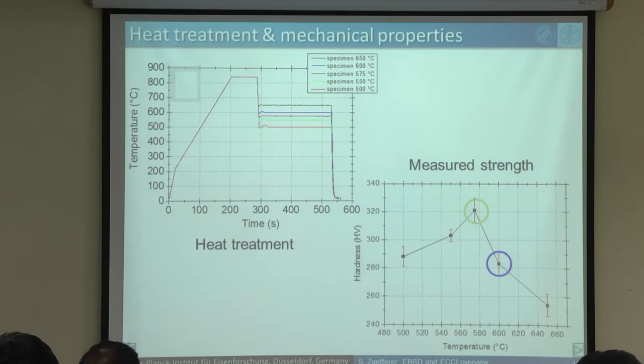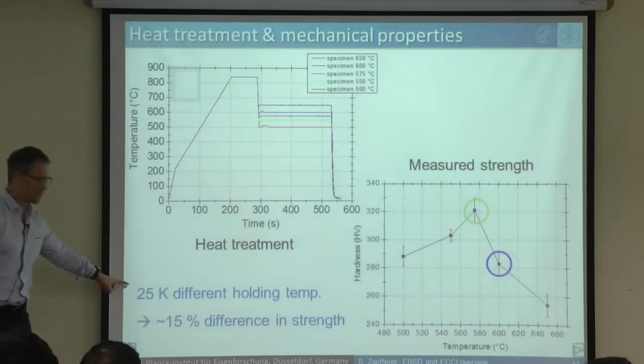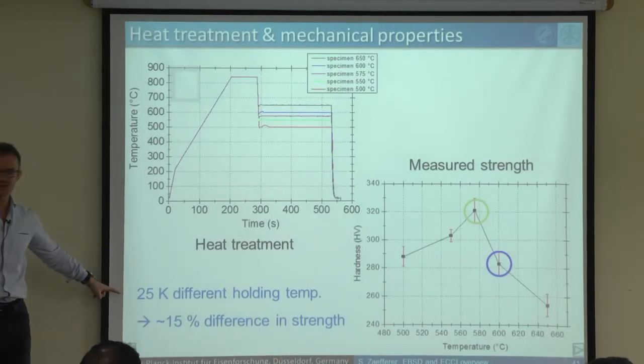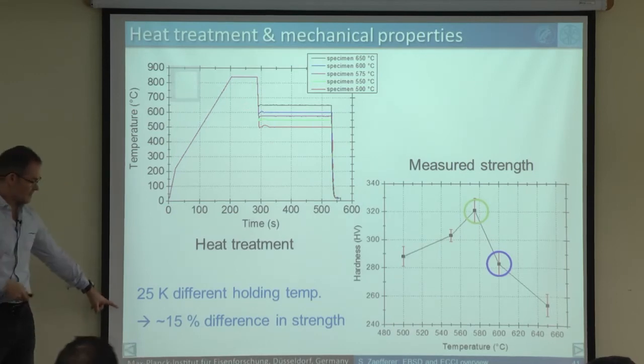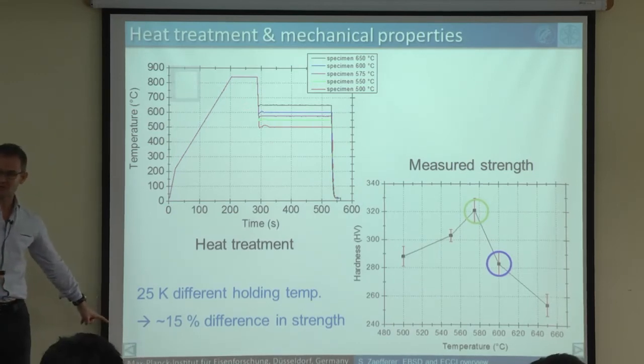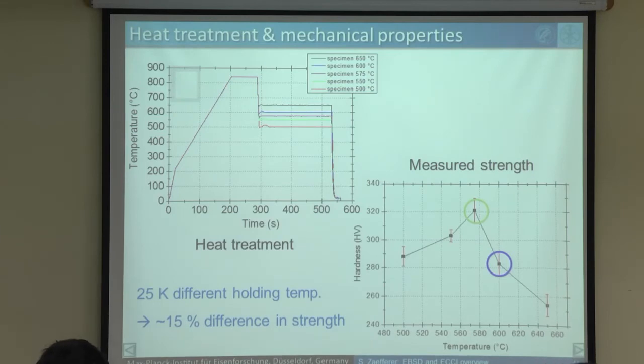And I just show you the two microstructures between this peak material and this cooled down at higher temperature transformed material. And these two, so yeah, that's important. We have only 25 Kelvin difference in holding temperature, but we get 15% difference in strength. So that's quite an amazing thing, and for the steel industry, certainly interesting whether it should go to 575 or 600 degree for holding, in order to gain 15% of strength. That's quite a good deal.